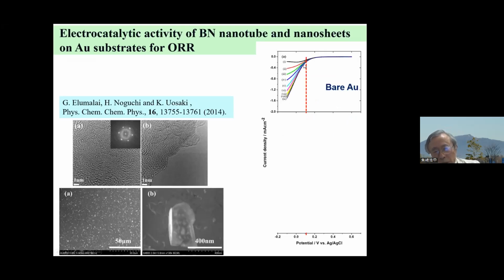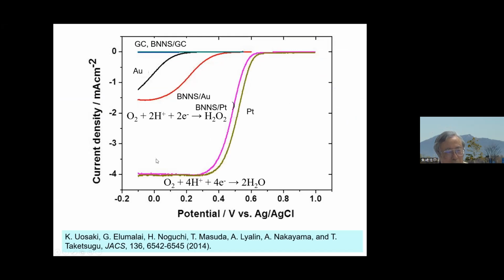So in this region, in the very small current region, the current is not affected by the supply of oxygen. In ordinary stationary electrodes, in the case of platinum, when the current becomes large, it is limited by the oxygen supply. Then in the earlier part, the reduction is controlled by the reaction. So you can calculate the expected theoretical current from diffusion, solubility, or concentration of oxygen and so on. So we can know the theoretical current density by knowing the rotation rate, the concentration, and the temperature.